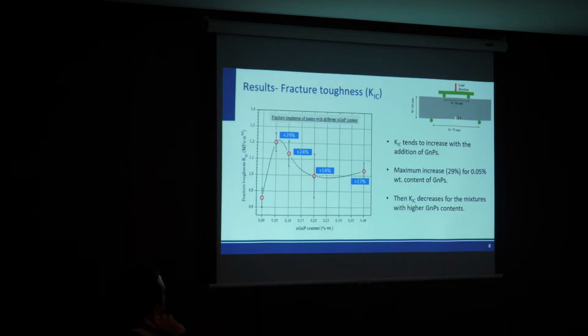With regard to the mechanical behavior of the specimens, we have investigated several different contents. On the x-axis, you can see different contents of graphene nanoplatelets, and as you can see, for the very small reinforcement of 0.05 weight percentage, you can have an enhancement of approximately 29–30%. This is according to the literature, because even at such small contents, reinforcement takes place, since they are reinforcing at the nanoscale. So nano cracks are prevented from propagating. That's why this enhancement is evident.